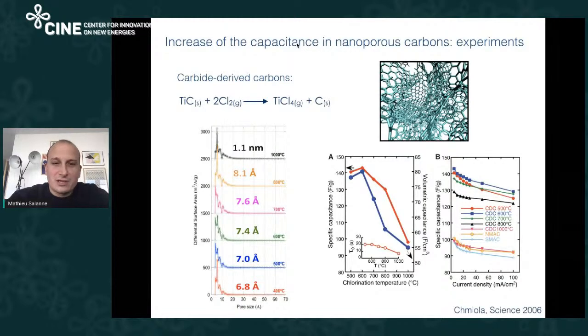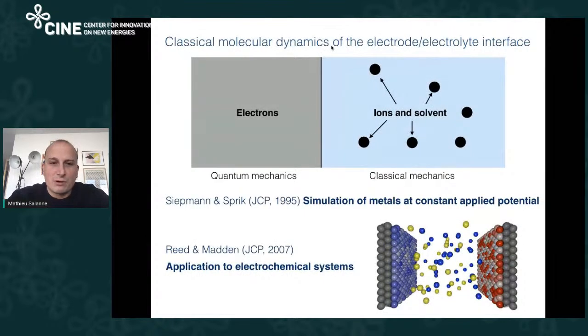And so you have very interesting effects that start to occur. You start to have confinement effects, and you are not limited by the surface anymore, and you start to trigger new charging mechanisms. For this reason, they were able to obtain larger capacitance. As you can see here, the specific capacitance, for example, could reach 140 farads per gram. And this is more or less 50% more than what was available before. So this was the beginning of our story, and we tried to understand this effect by molecular simulations. At that time, more than 10 years ago, we started to look at this problem. And in simulations, you have several ways to represent a problem.